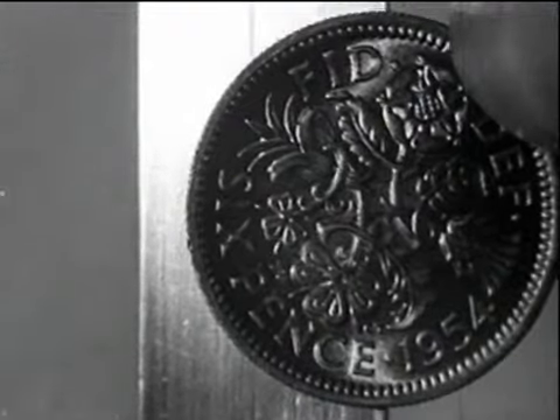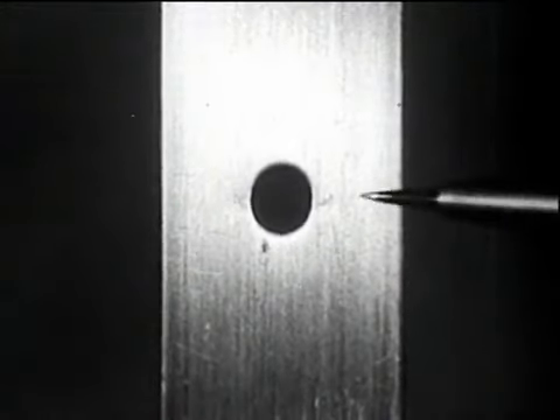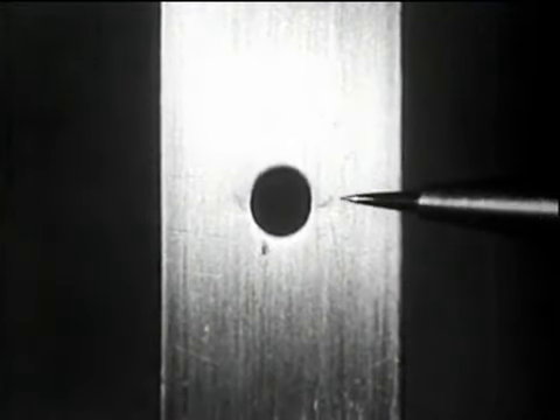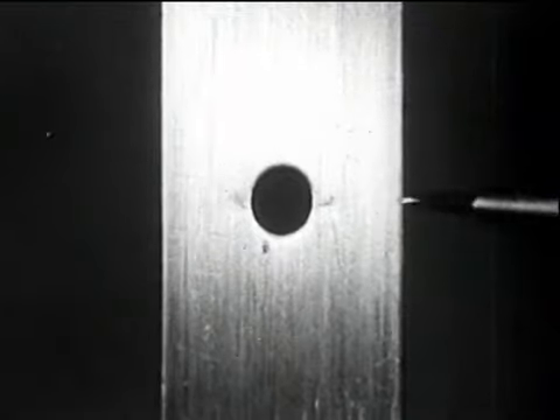A series of laboratory tests were made to study fatigue stresses around a rivet hole, and specimens of aluminium alloy sheet, similar to those used in the Comet fuselage, were stressed in a fatigue testing machine 2,000 times per minute from 0 to 40,000 pounds per square inch. Under these stressing conditions, the specimen fractures in about 6 minutes.